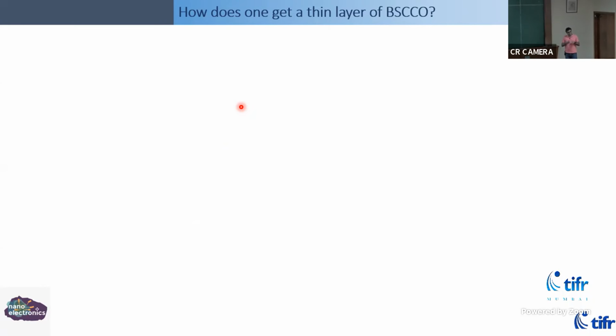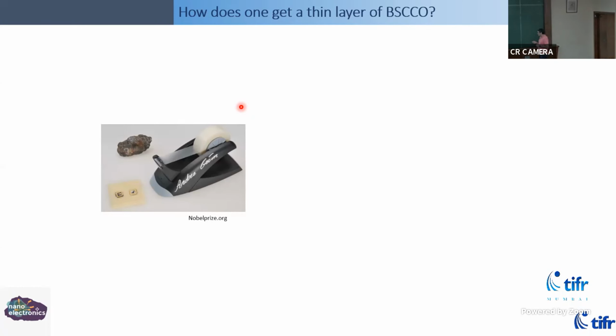So we often work with thin layers of BSCCO and other 2D materials. The standard method of peeling down to a few layers is a fancy word for peeling crystals using Scotch tape. It's called mechanical exfoliation. You put a crystal between tape and peel it off many, many times, and you rely on randomness, stochasticity, to find crystals of the thickness that you desire for your experiments. And when you put it on a substrate, I'll show you some images down the line, you will be able to tell from their color their estimated thickness. That's one way to do it.